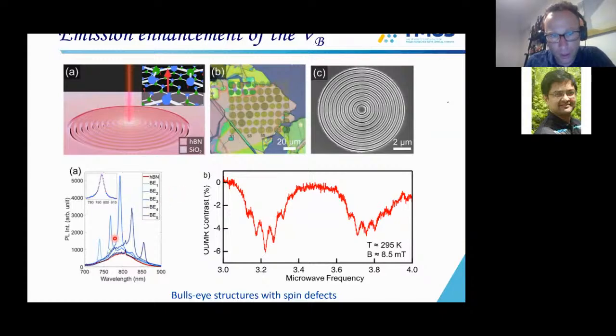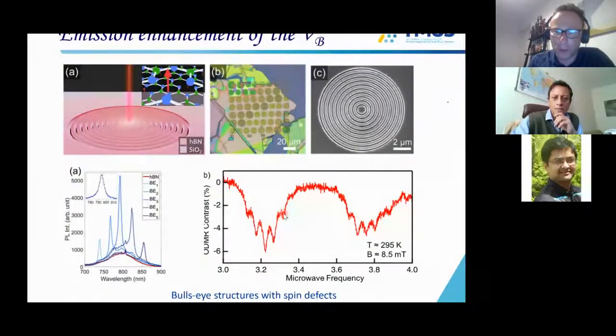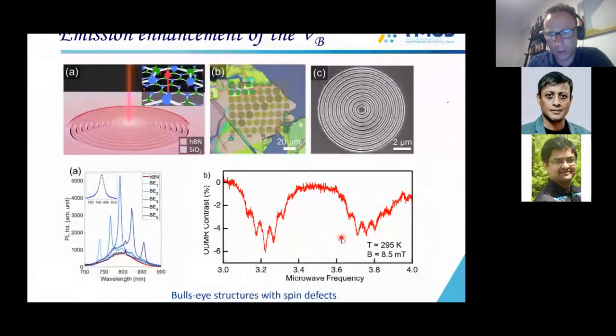And you can see here that you can tune the mode of this bullseye structure. And once you hit this resonance at around 800, the emission is enhanced and the signal to noise ratio of your ODMR contrast is improved a lot. So this is again from the Dyakonov group. You can see easily 6% contrast, and even the peaks are resolved in this ODMR spectrum. So it's really a nice result.